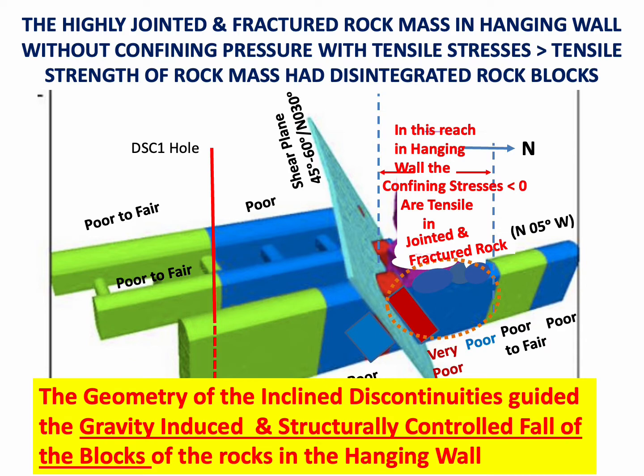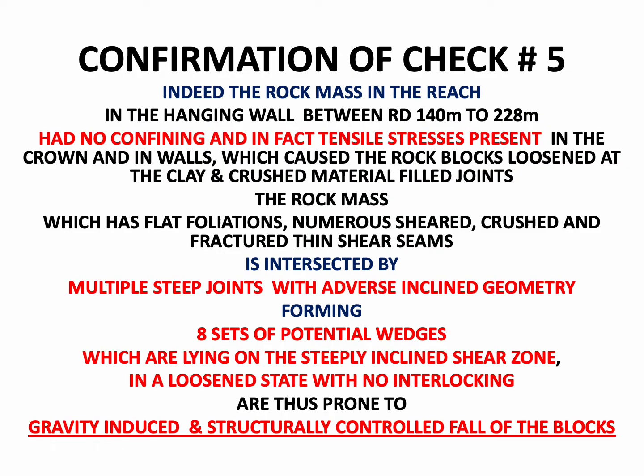The geometry of the inclined discontinuities guide the gravity-induced and structurally controlled fall of the blocks of the rock in the hanging wall. So this prerequisite is also met, that the geometry of the inclined discontinuities are guiding the gravity-induced and structurally controlled fall of the blocks. So the fifth prerequisite also confirmed. Indeed, the rock mass in the reach in the hanging wall between RD 140 to 228 meter had no confining and in fact tensile stresses present in the crown and in the walls, which caused the rock blocks loosened at the clay and crushed material filled joints.